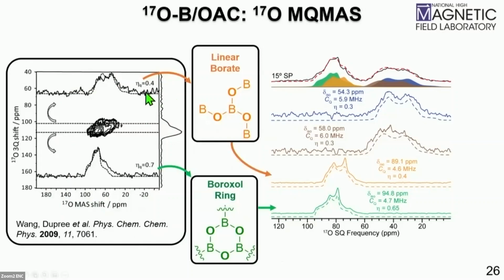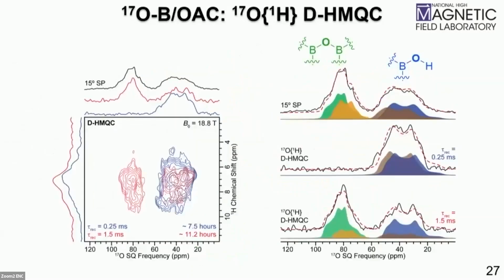And what they're able to show is that the low eta site corresponds to a bridging oxygen within a linear borate group, whereas the high eta site corresponds to an oxygen atom bridging within a ring. So this shows that this catalyst contains both linear and ring type borate species. We then also performed oxygen-proton HMQC experiments to confirm our assignment of this low frequency site to